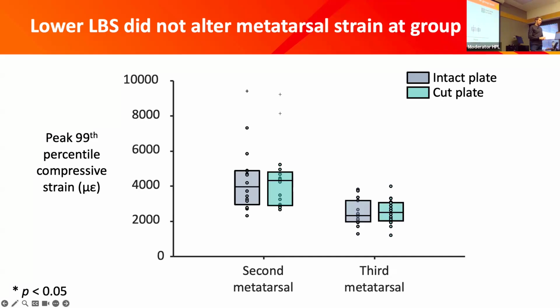All right, so now if we get into some of the results for the peak 99th percentile compressive strain in the second and third metatarsal here, you'll see plots for both the cut plate and the intact plate condition. And for the second and third metatarsal, unfortunately, we didn't see any effect of longitudinal bending stiffness on peak strain. So no significant change there. It was good to see that the third metatarsal strains were slightly lower than the second metatarsal strains. That's kind of what we'd expect, but no change due to the plate condition.